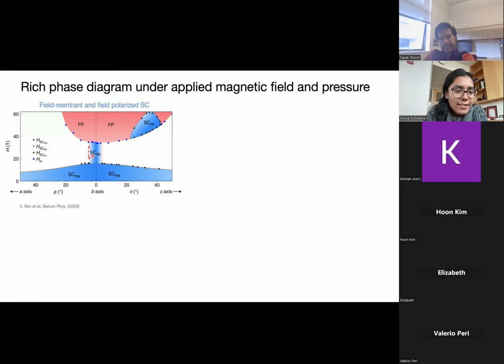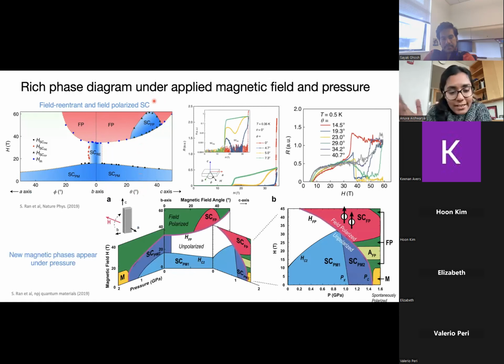Okay, so this is the B direction, where we see that there's a re-entrant superconducting phase that exists up to 40 Tesla, and the field polarized state, which is along this strange direction. So this is the 0-1-1 direction. This is important because when we try to cleave this material, it actually cleaves along the 0-1-1 direction. If we apply a magnetic field along the 0-1-1 direction, we see that superconductivity is suppressed around 10 Tesla. Then as you keep increasing it, it reappears around 45 and exists till about 60 Tesla. It's crazy. Similarly, pressure-dependent measurements show multiple superconducting states. Even new magnetic phases appear.